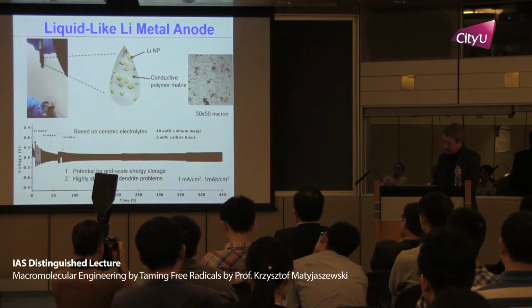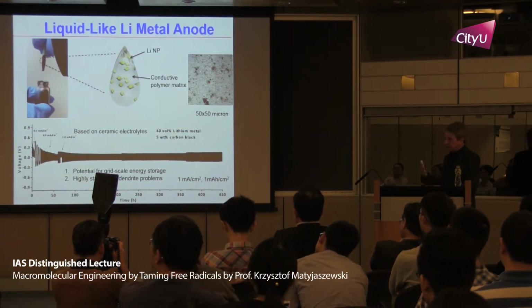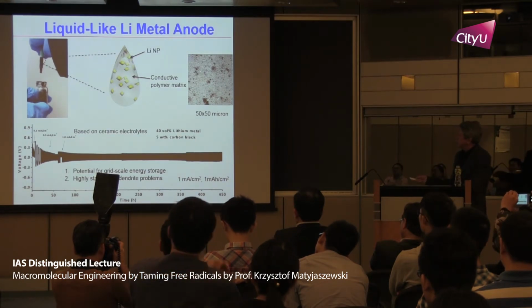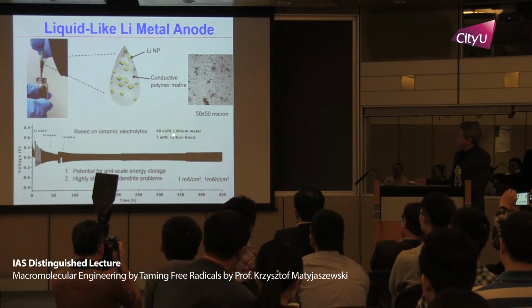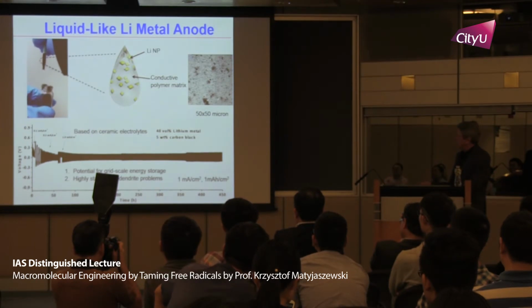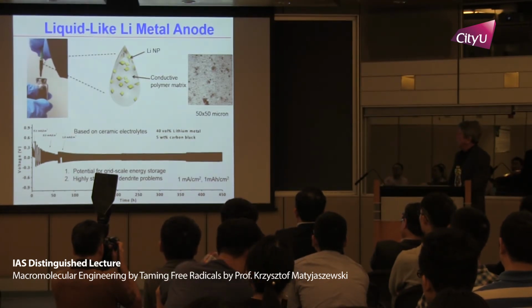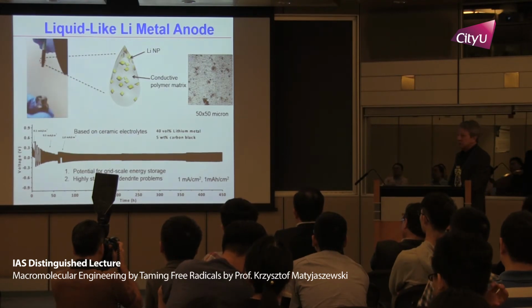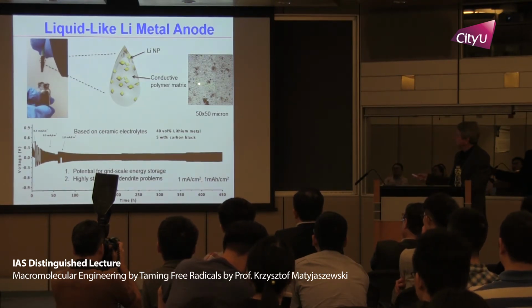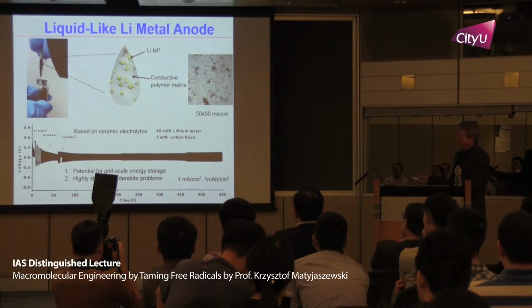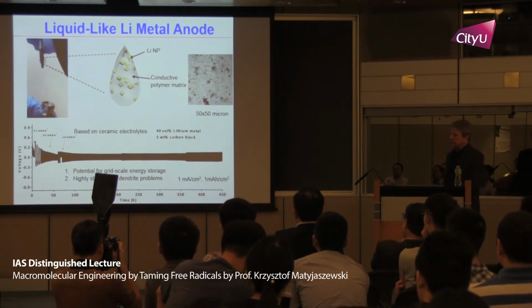So we prepared these alkali metal particles, lithium, and you could see this is 40% lithium metal in a polymer, with 5% of carbon black, and this is how it performs. It's really the size of these lithium nanoparticles. This is 50 microns, so it's a sub-micron system.